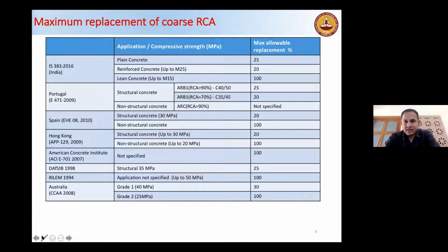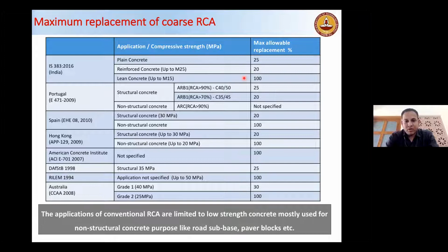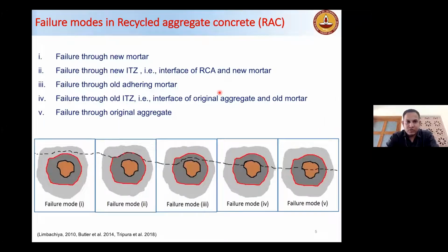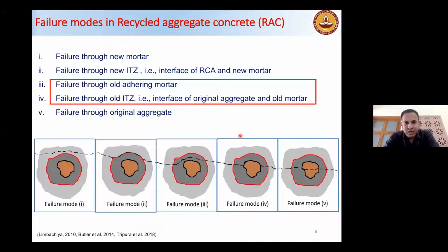There are many standards, but 100% is allowed only for lean concrete, and 20 to 25% is allowed only in plain and reinforced concrete applications, which are limited to sub-base, paver blocks, or non-structural applications. And then you have seen these failure modes also. So out of these failure modes, there are two common failure modes, which are failure of this adhered mortar, and there could be the failure at the ITZ between the old adhered mortar and the original aggregate.